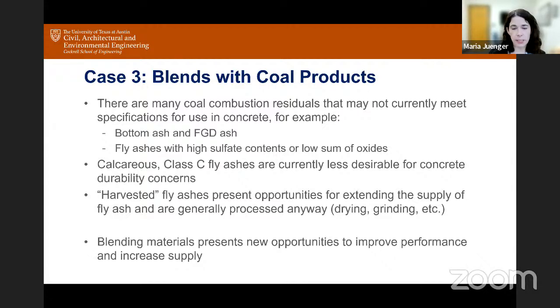We also have fly ashes that don't meet specifications. For example, in the US, ASTM C618, which specifies fly ashes, has boundaries on a lot of things in the fly ash, including the sulfate content and the sum of oxides and other chemical properties of the material. Right now, those are not allowed to be used in concrete under ASTM C618. It doesn't mean they're not allowed. You can always go off spec. But according to the specifications now, these are not allowed materials. The other interesting issue we have in the US is that the Class C fly ashes that have higher calcium are now considered less desirable materials to use in concrete mixtures because they don't assist with our workability and durability of concrete as much as Class F fly ashes. So they are less used, which means they are more highly available.